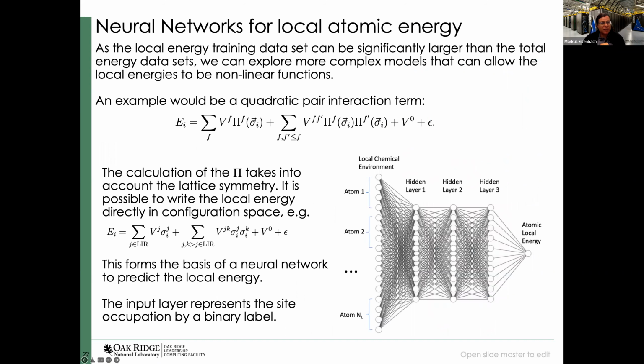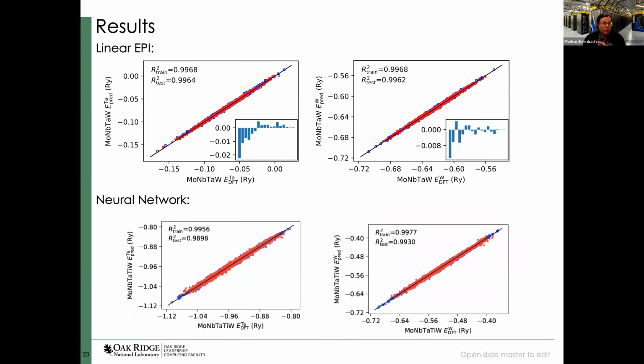In addition to the pair interaction model, we also apply the same idea to using a neural network, where we basically have a one-hot encoding of the different atomic species on each of the lattice sites within this local interaction zone, multiple hidden layers, and finally getting this local energy contribution. Now, for simplicity, I don't show the additional constraints that can be built into this model ultimately, but that's also still work in progress.